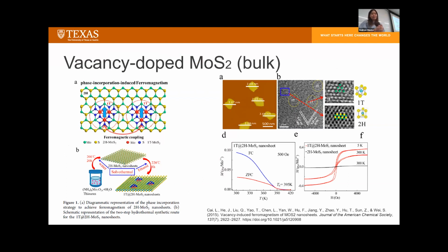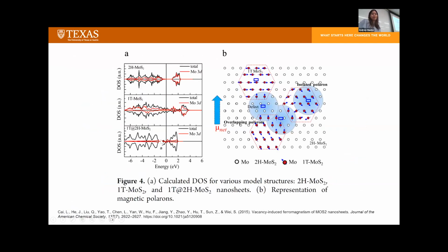The last work I want to show is vacancy doped MoS2. It actually doesn't contain any ferromagnetic atoms, but it has different phases of MoS2 in the whole film, and they observed room temperature ferromagnetism in this kind of material. This is their calculation of the density of states.